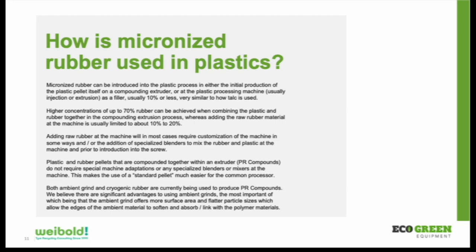So that's really what we're doing. We're never really melting the vulcanized material. We're just using the material as kind of a hybrid filler that does absorb the oils from the olefins and allows the material to play nice with the plastics. So again, we believe that the ambient ground material is a much better material because it's truly locking together with the olefins, whereas the cryogenic materials are just touching at certain points.